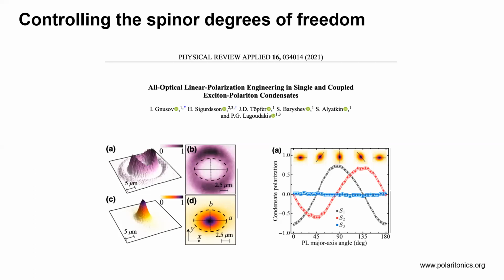So if I create an elliptical trap, not a spherical trap, so I pump with an ellipse, I see actually that I pin the polarization, the linear polarization of the condensate on the short axis of the ellipse. So that was some initial work that we did in 2021. We could create a condensate where by rotating the ellipse very slowly, not with combined beams, just with conventional optics, we could really rotate the linear polarization of the condensate. But now we can rotate it with gigahertz. So let's see what happens.